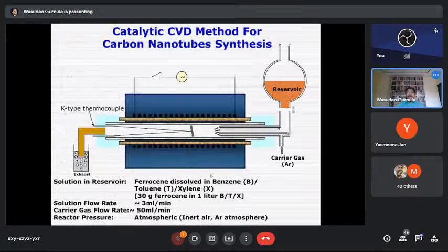So here the CVD method consists of this type of arrangement. The reservoir shown here is nothing but a solution of ferrocene dissolved in benzene, and through this outlet we have to pass argon as the carrier gas. Here is a K-type thermocouple. This CVD method is the most widely used method for carbon nanotube synthesis. For this purpose, the metal nanoparticles are mixed with a catalyst support such as magnesium oxide or aluminum oxide to increase the surface area for higher yield of the catalytic reaction of the carbon feedstock with the metal particle.